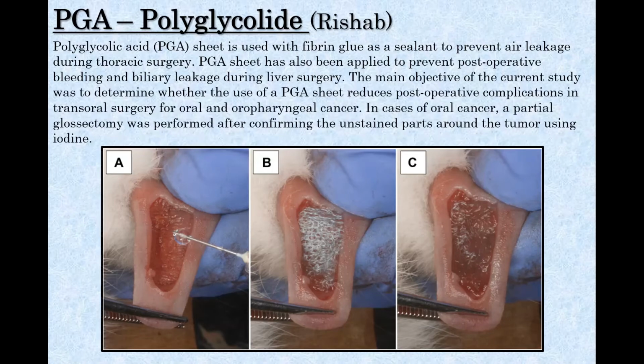PGA possesses excellent mechanical properties, specifically the highest elastic modulus of 6 to 7 GPa in comparison to other bioresorbable synthetic polymers such as PLLA, PDLLA, and PCL. The Tg of PGA is higher than the ambient temperature. However, its Tg could be lowered due to water absorption in the body environment when it is inserted as an implant. Next we have